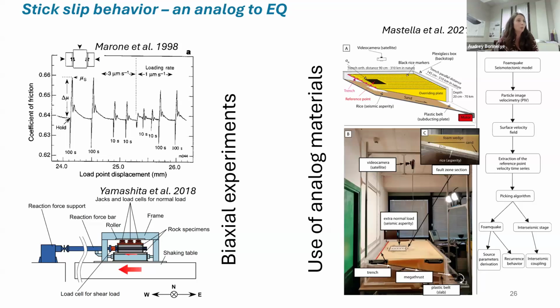So some people, and among those people, of course, Chris, have been developing some shearing apparatus in order to investigate those parameters more easily, in the sense that they have a better control. So you have the double shear experiment that is presented here, and people have been doing, again, many experiments toward that direction. Many people have then started to look at what happens if you put bigger blocks, because one of the limitations of the experiments that were done is actually the size of the sample. And so there are some phenomena that you can only see on a bigger sample. So here's an example of some work that is done in Japan to look at the sliding surface.